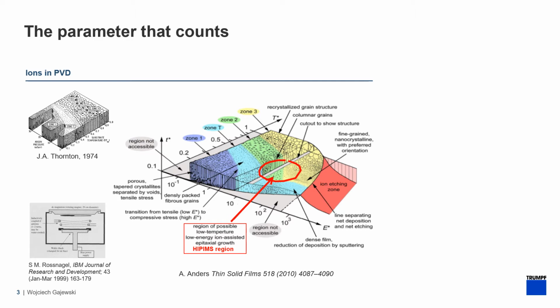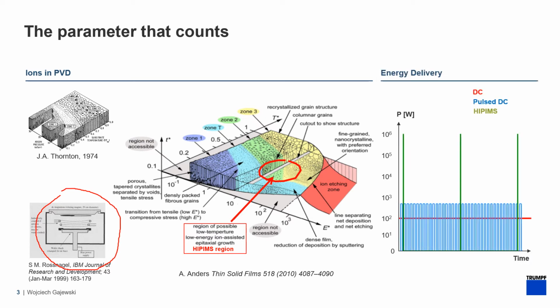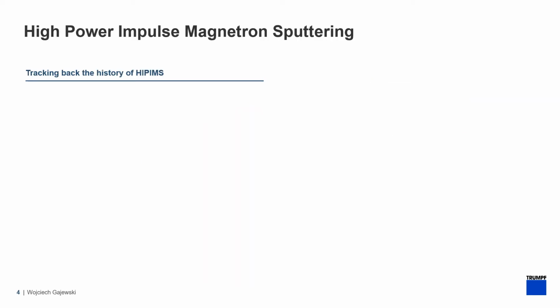So how to control the ionization and not to use a combination of magnetron and ICP coil to do that? Well, the idea is simple. Instead of using a DC or pulse DC, we can use high energy pulses as we do in HIPIMS, and with these high energy pulses we can get high ionization of the sputtered species.